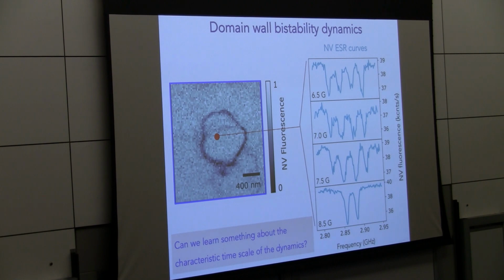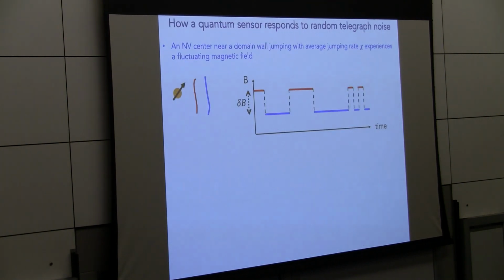The answer is yes. Let me explain a little bit how we realized that we could do this. This really relies on the fact that we're using this quantum sensor. Let's say we have an NV center sitting next to a domain wall that can reside either in this position indicated by the red line or the blue. And say the domain wall is jumping between these two spots with an average jumping rate chi. What the NV center is going to feel is a magnetic field that's high when the domain wall is close, and low when the domain wall is far away.